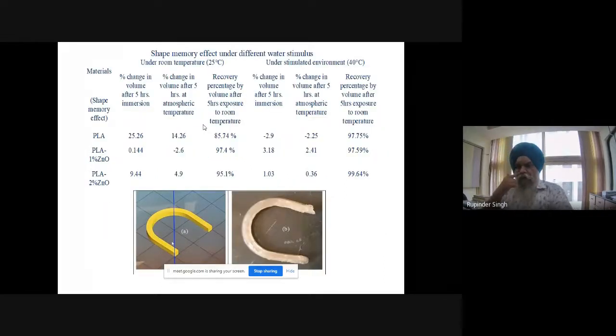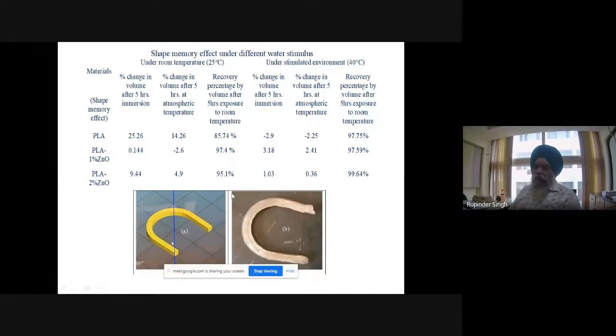Now this will be important to understand. So I printed a component like a U, right? So I tried to see what is the effect of water as a stimulus. So basically for 5 hours I put that material in water, and after 5 hours we tried to see what is the volumetric change. Then putting it for 5 hours at 25 degrees Celsius temperature, we tried to see how much change in shape is there. Basically, either this U is getting rotated into a V, or the outer face has an inward movement, right?